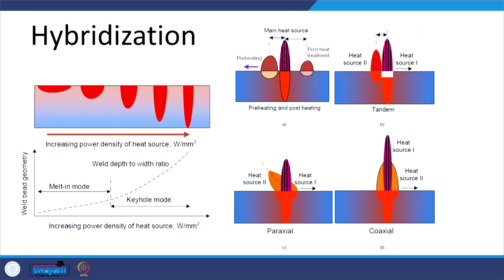So, what happens when we work with the low power density? Our weld penetration is less, width is more. Increasing power density increases the penetration, reduces the width, that is what we can see. So, high power density helps in realizing deeper penetration, but a narrow weld, because the approach of welding changes. When we work with the low power density, our approach is melt-in mode, but when we go with the higher power densities, then keyholing is realized. So, when keyholing is realized, we achieve the greater weld depth to width ratio.